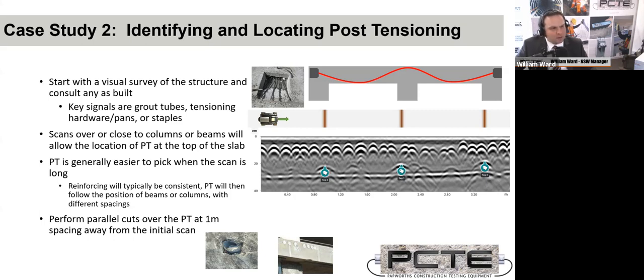So when there's something you didn't see, you need to get back to a place where it may be easy to see. That's why we say getting close to the columns, where you might expect your reinforcement to be close to the surface and easy to locate, especially if you're not able to see it, say in the midspan of a beam where it could be quite deep, maybe below that 700 mil threshold. And as I said, the depth you can go to is going to depend upon the moisture content of that concrete. So always look for the things you expect.